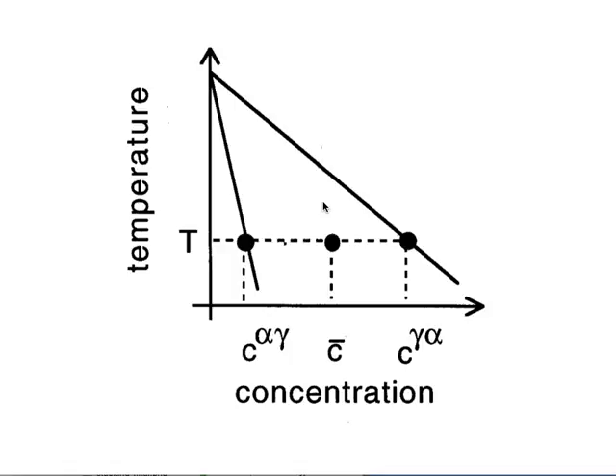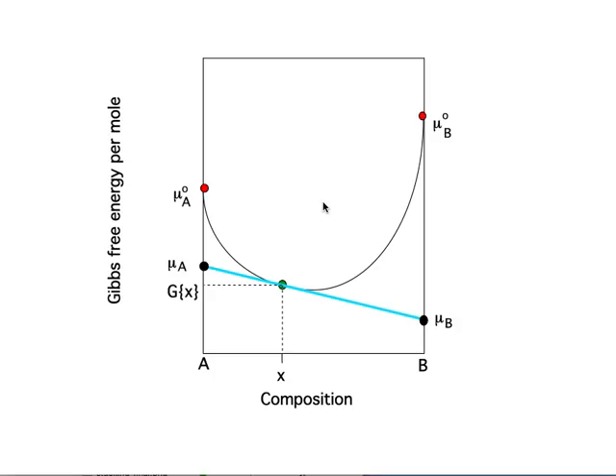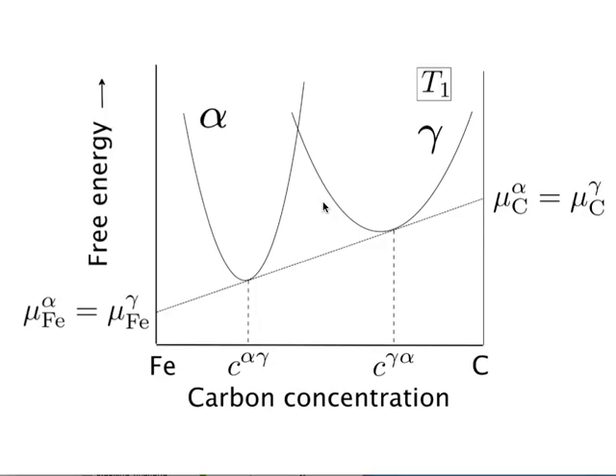Okay, so just a revision again. When we were dealing with the binary system, we could define the conditions at the interface by drawing a tie line at the transformation temperature. The tie line basically means that the chemical potential of B atoms in alpha and gamma is identical, and the chemical potential of A atoms in alpha and gamma is also identical. So even though they will be of different chemical compositions, there will be no tendency for diffusion when these are in contact, right? Because it's the free energy gradient which drives diffusion, and the free energies of carbon and iron are equal in both phases, right? So this is how we construct a phase diagram: we draw a common tangent.